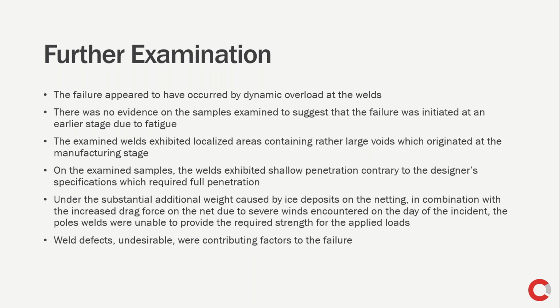overload at the welds. It was not only the ice formation on the netting, it was also the drag that was caused by the wind. And the conclusion was that the failure was possible because of a combination of factors, like undesirable defects in the weld associated with weather conditions.